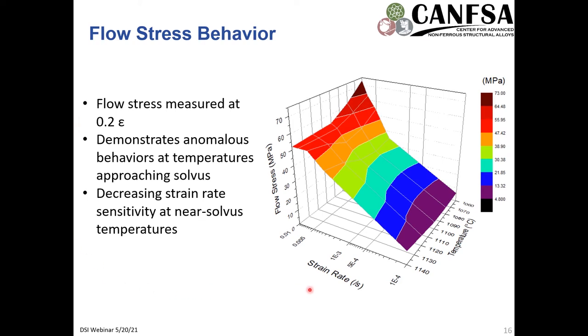And so we're looking at flow stress as a function of temperature and strain rate. And we were able to see that as we increase the temperature of the isothermal forging, we observe a decrease in the strain rate sensitivity, and there are some anomalous flow stress responses that we observe in this regime over here. And so we'll go into a bit more detail about that.